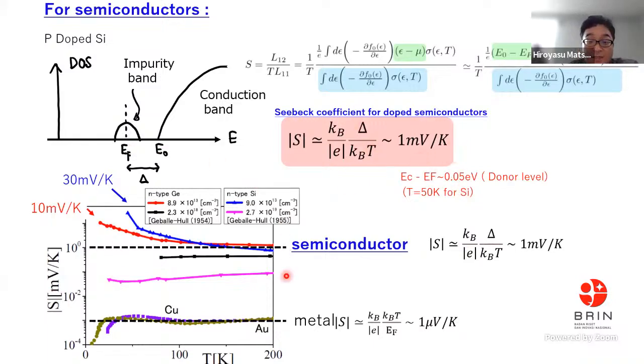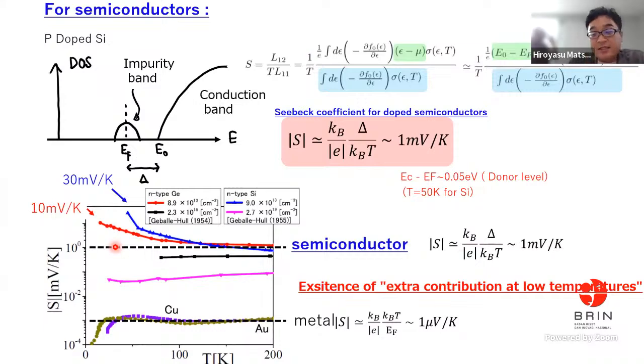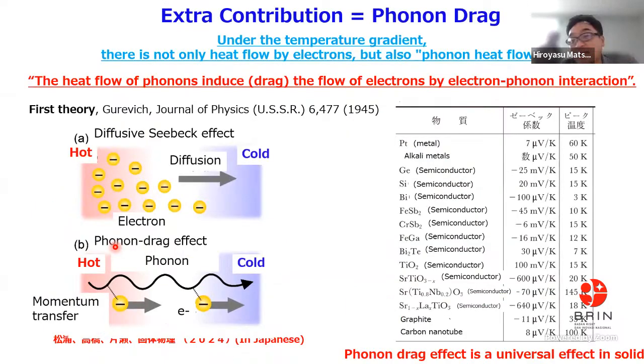But this is an experimental result. The blue line corresponds to the N-type silicon, low doped case, and this is a germanium case. We have these dotted lines corresponding to these ones, and we have a deviation from the theoretical result. Yes, we have the additional term. So what is the origin of the additional term? The origin is the phonon.